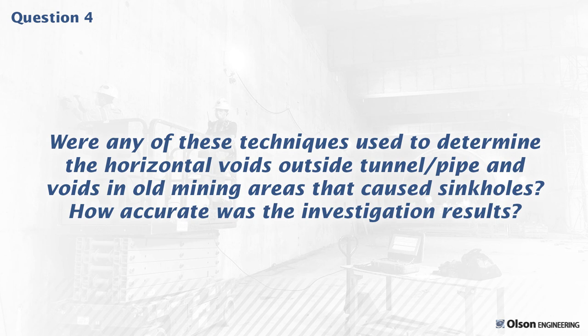Q: Were any of these techniques used to determine horizontal voids outside tunnel pipes in old mining areas causing sinkholes? Our principal geophysicist Dr. Ryan North has done a lot of work on karst and sinkholes, but these particular techniques wouldn't necessarily be the approach for that. With radar, it's very unusual to see the thickness of a void outside a tunnel because the energy is so attenuated by the reflection at the void — whether water-filled or air-filled. We'll map the location, but destructive testing or exploration is normally needed to get void thickness. We have seen top and bottoms of voids under slabs, but probably less than 10% of the time.